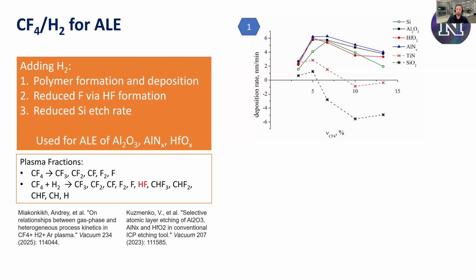We're also pretty happy that there's a lot of hydrogen here, because we want more HF formation and less fluorine formation. We want to control the amount of free fluorine to avoid spontaneous overetch into silicon in case we're using this as a post-treatment. So we've already etched our structures in a standard RIE process. Now we just want to use ALE to clean up our surfaces and remove that damage. In our case, we're actually doing all our full etches with the ALE process, but others might want to do it differently. We already know this approach reduces the silicon etch rate. This has been studied. Awesome.